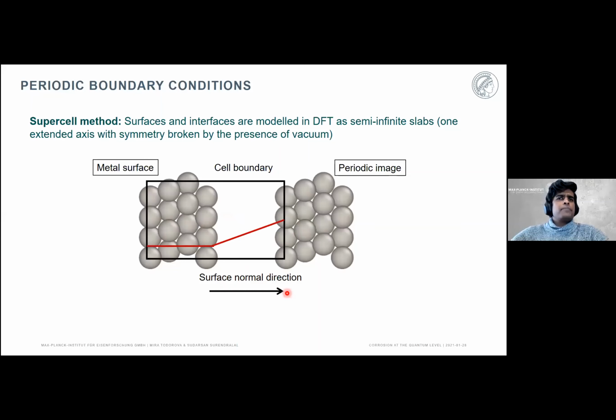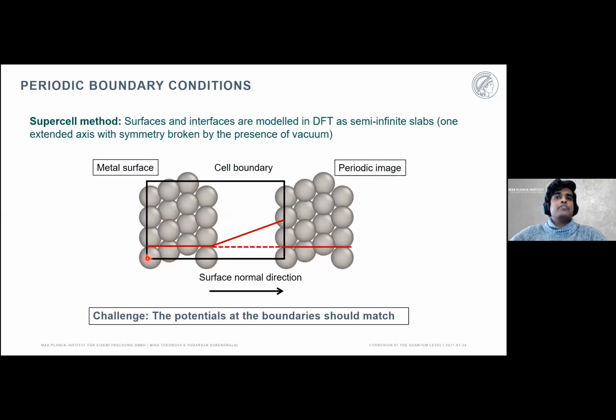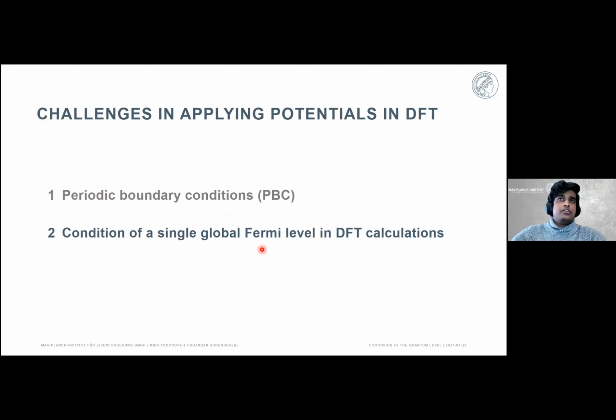Now, in order to apply a potential bias between the two electrodes, you will have to apply a potential that looks something like this. However, a certain limitation is that because of periodic boundary conditions, this point and this point, the atoms at this boundary, and the corresponding potential should be equal. In other words, the potentials at these two points should be exactly the same, and there shouldn't be any sort of discontinuity in the potential. This is one challenge in applying electric bias for these calculations.